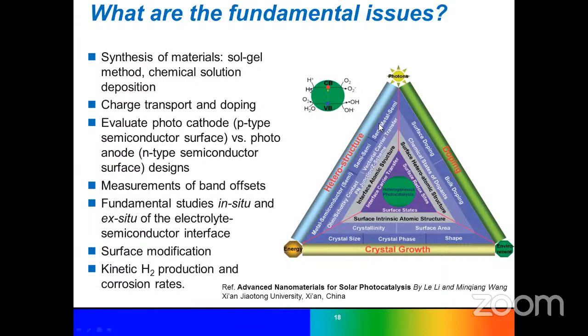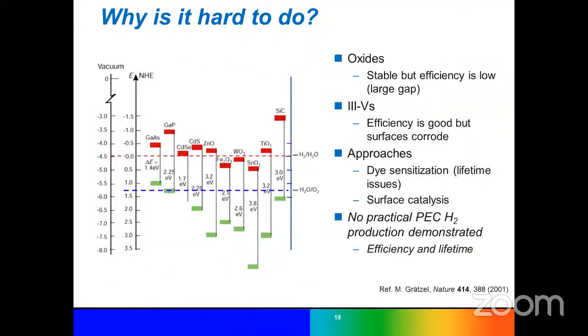And if you see this triangular diagram, there is the crystal growth, different types of size of the crystal, phase, shapes, bulk doping, surface doping, chemical state of dopings, and then interface atomic structure, all are correlated to each other. So when we are making the photoelectrode, we have to optimize this doping, heterostructure, and crystal growth all together. And then we optimize and get this high performance photoelectrode material. So if you see the periodic table, there are different types of materials available, but some have both advantages and disadvantages.